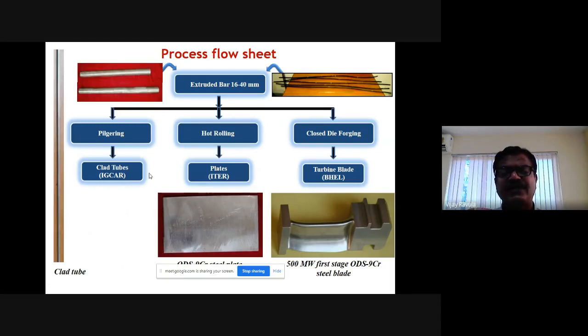And this is an extruded rod; we get a 40 mm rod. When you do the pilgering, you get a clad tube for the fast breeder reactor. Then you do the hot rolling, you get plates for the fusion reactor. And then you do the closed die forging, you get a blade for the steam turbines. So these are the turbine blades we made for the 500 megawatt first stage turbine.